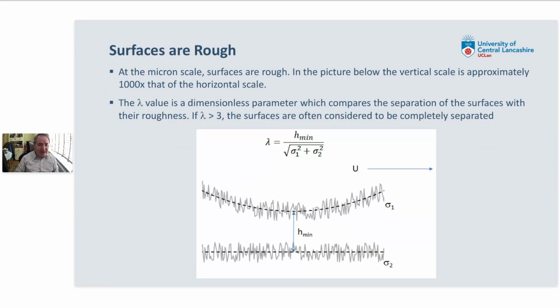And depending on how the component has been manufactured, there will be a probability distribution function associated with that roughness. And you can define a root mean square roughness of the surface, which we call sigma 1 here, and similarly for the flat surface there's a sigma 2. And if we compare the film thickness to the square root of sigma 1 squared plus sigma 2 squared, we can define something called the lambda ratio, which effectively tells you how far apart the rough surfaces are separated. And you need a lambda value of about 3 or more to completely separate the rough surfaces. And if the lambda value is less than that, then you will start getting the rough surfaces interfering with each other and touching each other, and you'll get wear and friction occurring.